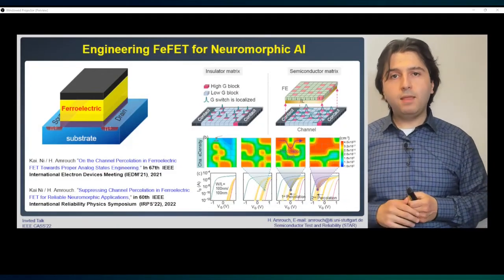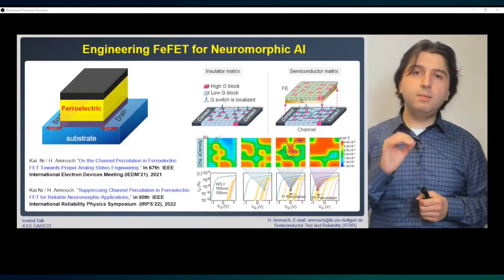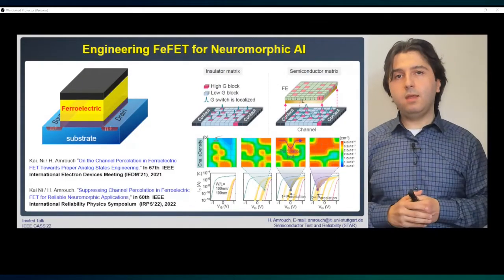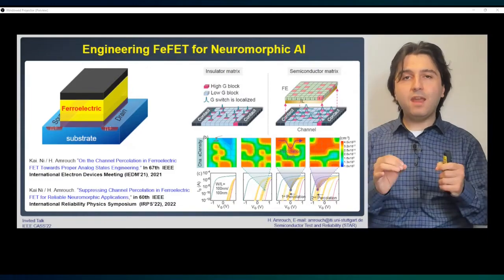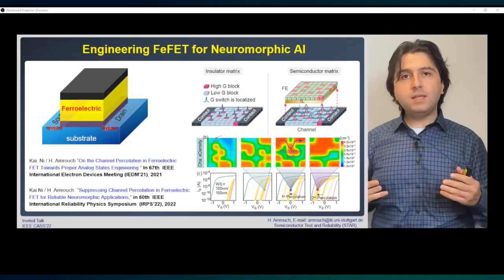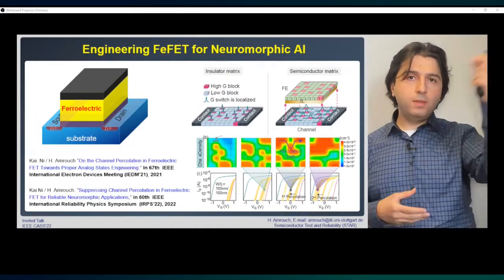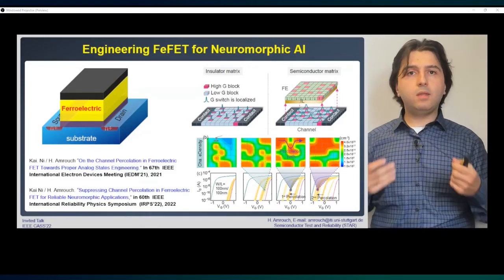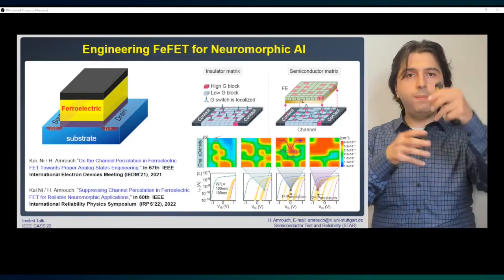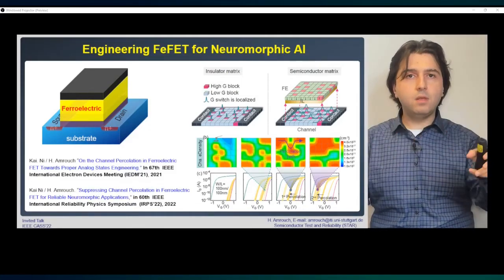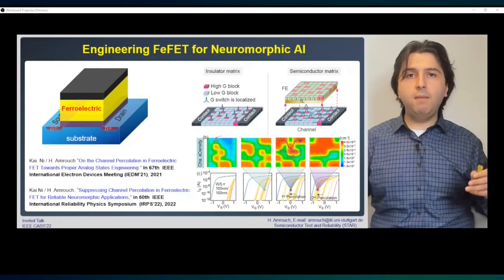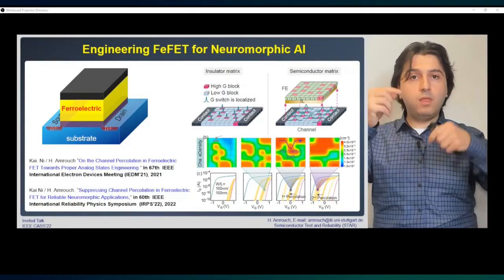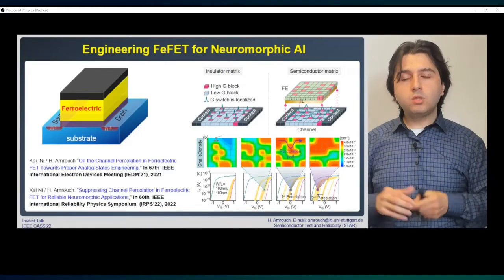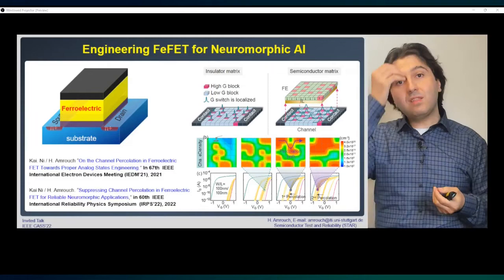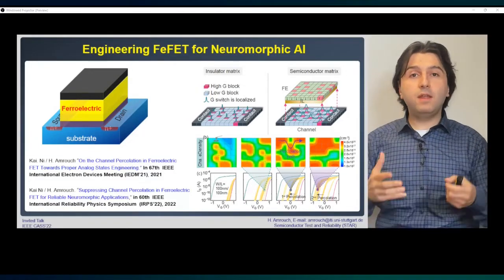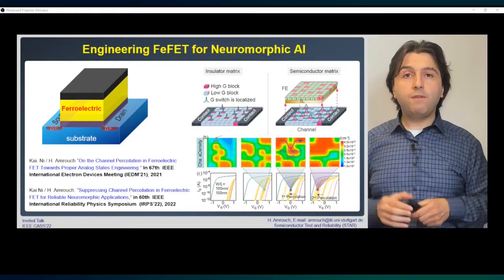Before explaining that, let me add on top an additional, extremely challenging and not yet studied in detail source of variability. It comes from the inherent stochasticity in the material. As expected, you have a new material that you are growing by doping zirconium into hafnium, and this doping creates the ferroelectricity, and you have different grains. Those grains have different sizes and different shapes, and as a result, they will interact with the channel in a very different way. So this is a stochasticity that imposes an additional source of variability that is very difficult to live with. In fact, the first step is you need to model it.